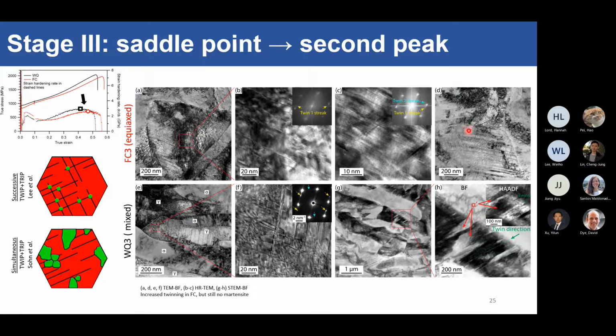And then you have these thick twins here. So twins, as they deform, they get thicker, and that happens in TWIP steels as well. So good to see thick twins here. What's interesting now is in the water quench sample here. So we can see in the lamellar grain, finally it starts to twin. You know, I made a twinning steel. So it twins in this direction here, and at the tip of the lamellar grain where you have a very high stress concentration, you actually activate both twinning systems here. But again, if you look at the diffraction pattern here, turquoise and yellow, those are the twinning spots. Again, no martensite spots, no martensite at the twin intersections in this grain.